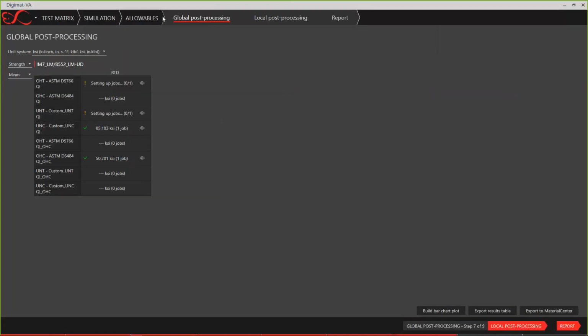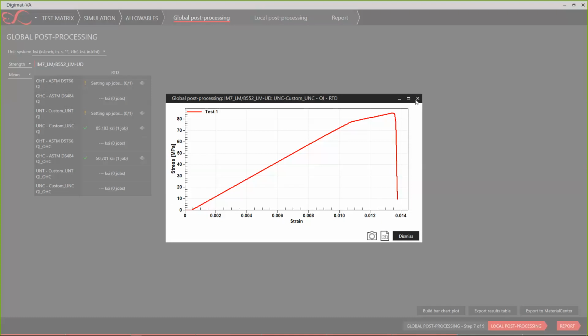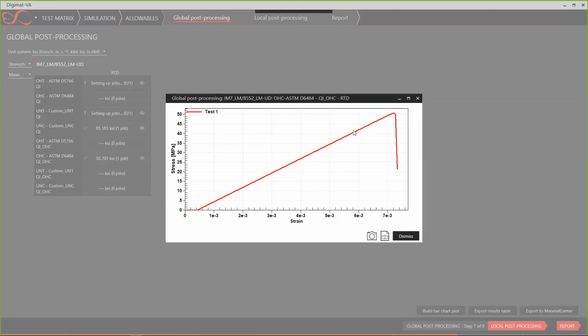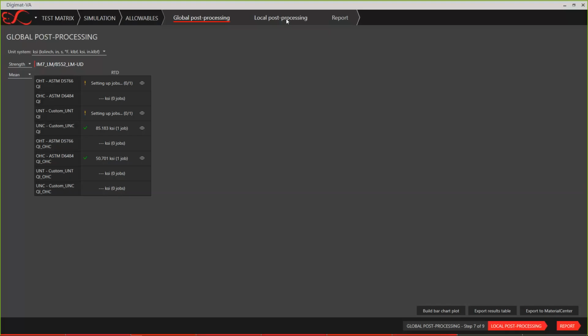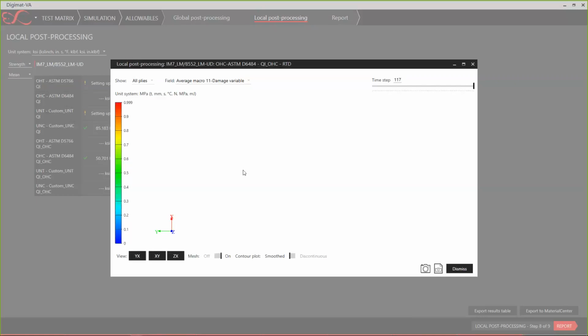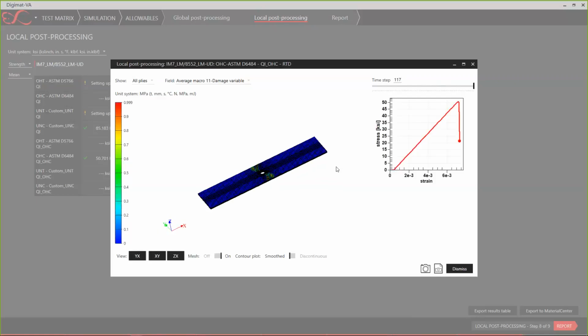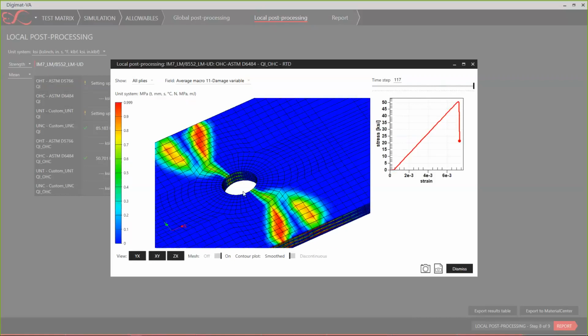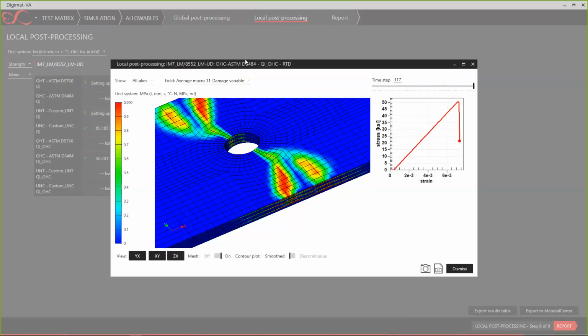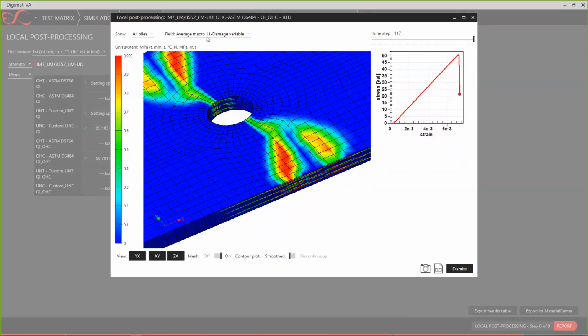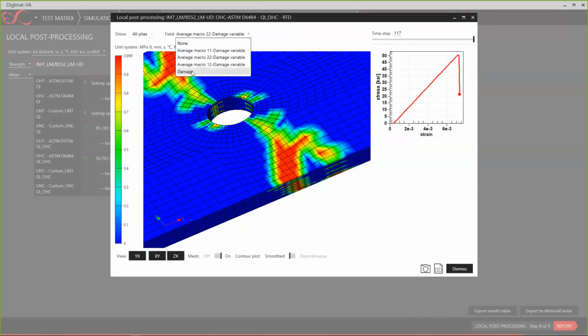For the post-processing, I can go directly in the allowable tab, and we have two levels of post-processing. We have what we call the global post-processing, which gives the stress strain curve. Typically, for each step you can visualize the stress strain curve, and you can have information about the strain value that has been measured. You also have the possibility to do a local post-processing. Local post-processing will give you access to the detailed post-processing inside the coupon. Typically you can visualize the damage variable: the damage variable in the axial direction, the damage variable in the transverse direction, and the damage variable in the interface, so the delamination.